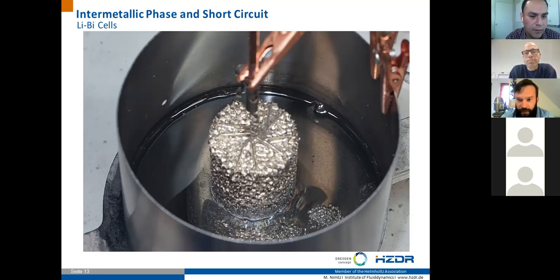More questions from the audience? About using tantalum crucibles, will the use of this material not increase the cost of the battery? Yeah. Of course, the tantalum crucible is used only for the experiments in the glove box, to be able to have a view inside the cells and to be sure that there is definitely no side reaction. The idea for commercial cells is that the tantalum will be replaced by stainless steel. It is not known of which grade yet, but it will definitely not be tantalum or something similar, because it's much too expensive.